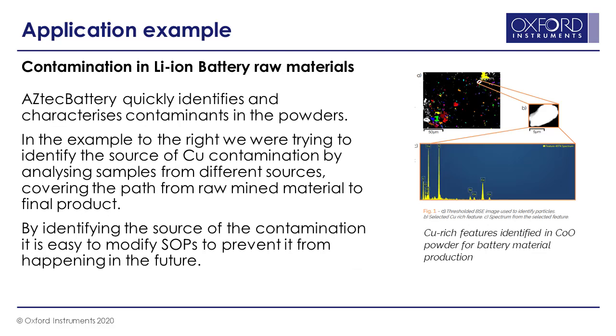By taking powder samples from essentially the mine, trucks, transporters, and all subsequent processing steps, we can quickly characterize and identify all particles and see at which point contamination particles appear. In this example, we can verify there is no copper contamination when the powder comes straight out of the mine, but we can see that air samples taken from the trucks used for transport actually have copper particles on them. It's not just powder samples we can examine — samples from air filters also help identify where contamination particles appear in the environment where the material is being handled or processed.